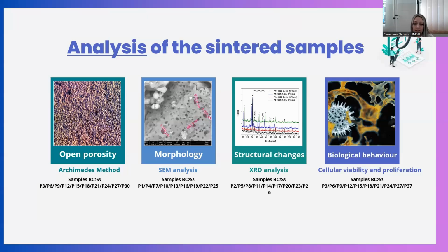Regarding the analysis of the sintered samples, first of all, we calculated the open porosity, which is an important characteristic for a biomaterial and for a scaffold used in tissue engineering, using the Archimedes method. Then we looked at the morphology of the samples by SEM analysis. We looked for some structural changes using XRD analysis, and our partner did some preliminary biological tests regarding cellular viability and proliferation.